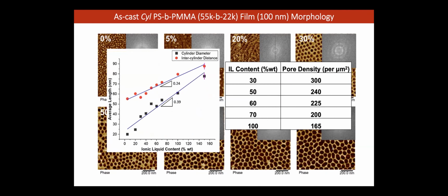So then we can do very simple analysis like average diameter of the cylinder, inter-cylinder distance, and get power laws. And you can see them here. And the pore density, as you add more ionic liquid, of course, goes down because the pores get bigger. For membranes, this is really important, the pore density and the pore size. And there is no real study of where the flux optimum is from a filtration standpoint, because on one hand, pore density is great, but larger pore size would also give you higher flux. So there should be an optimum in that sense.